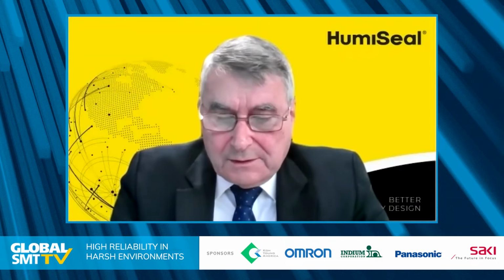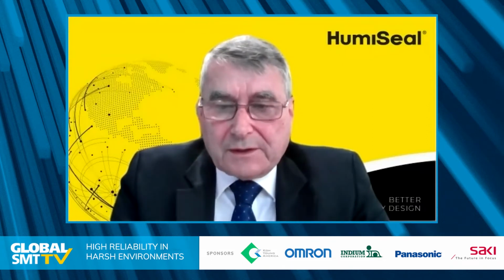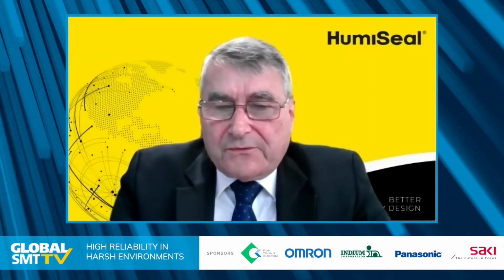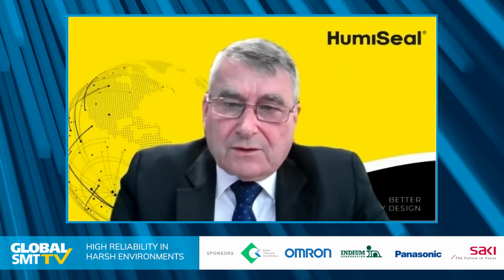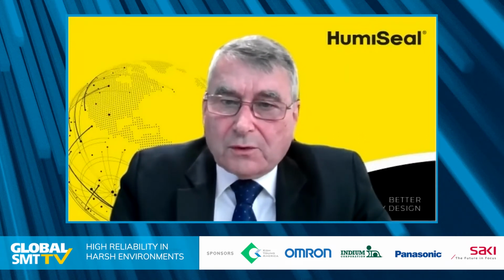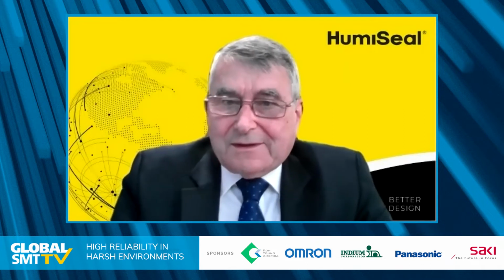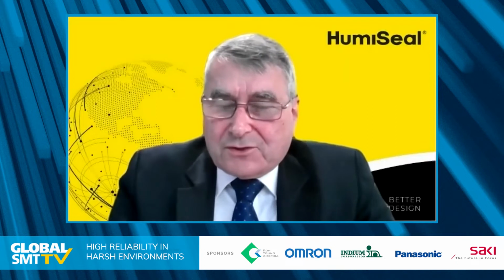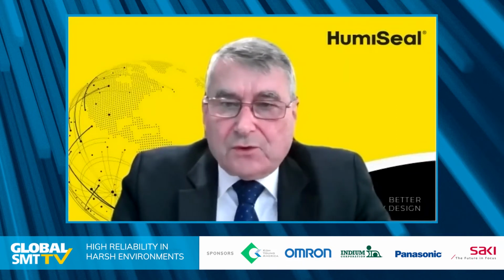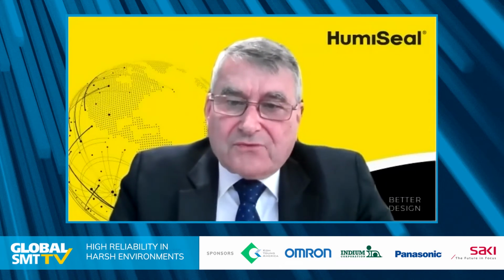Yeah, I think one thing I would like to just quickly add with reference to the lead-free and cleaning. We've done some work recently, and I know that our R&D manager, Chris Brightwell, presented it at SMTA, about the effect of vitrified flux on a lead-free, no clean board when you put a coating on top of it. And of course, today, the automotive industry is wanting thermal cycling -40 to 150, as we've said before, and anything between 1,000 cycles and 3,000 cycles.